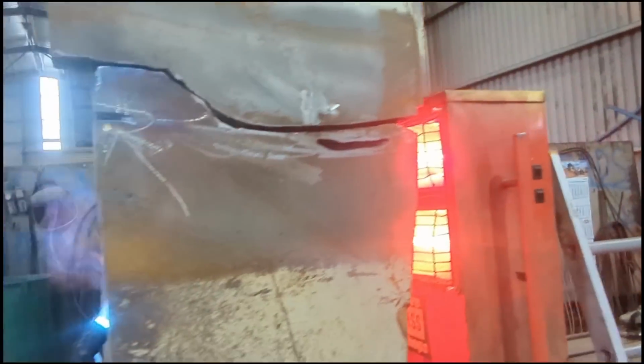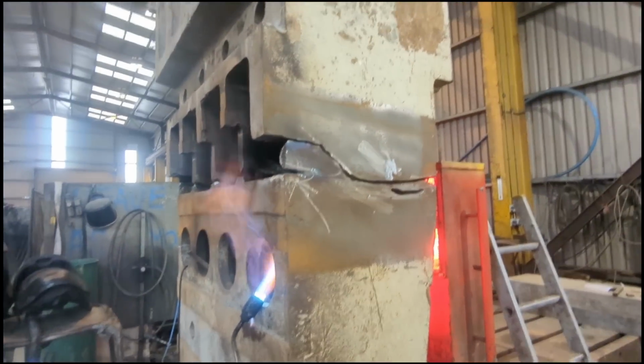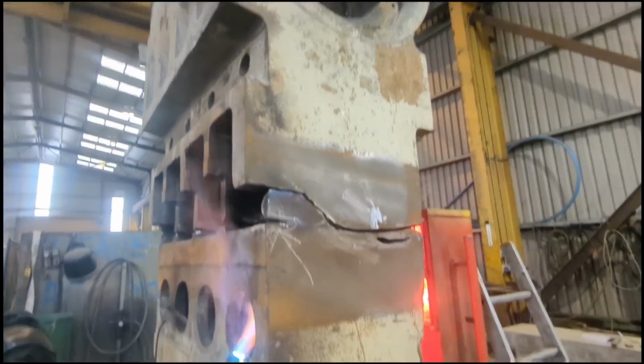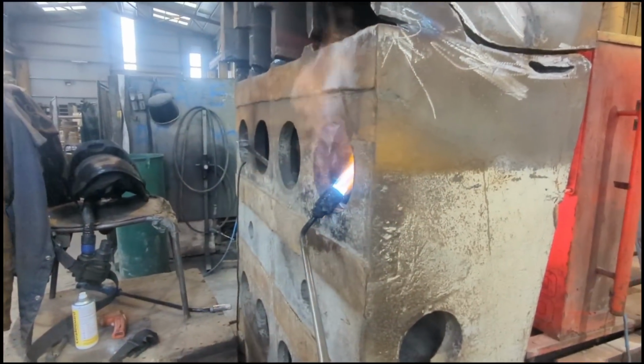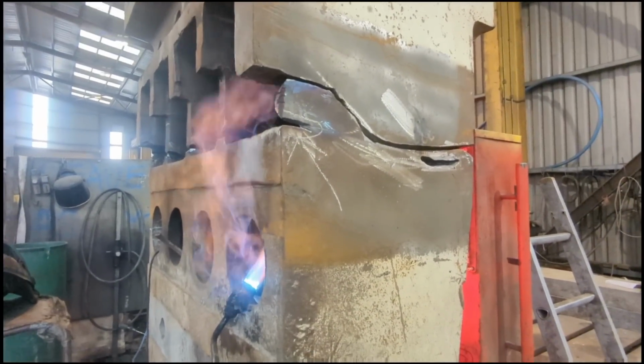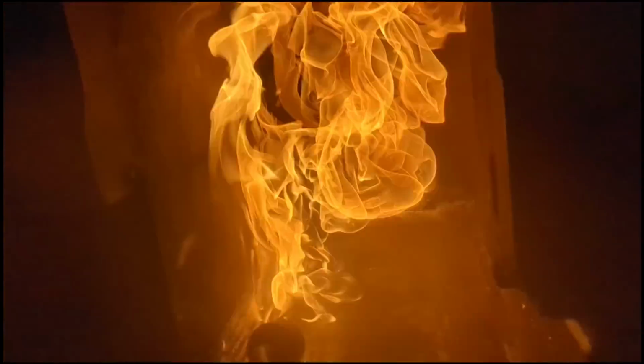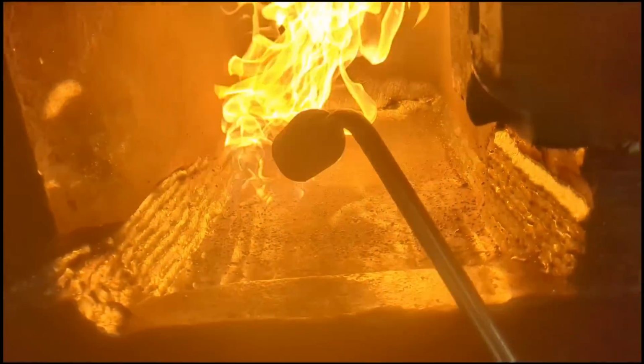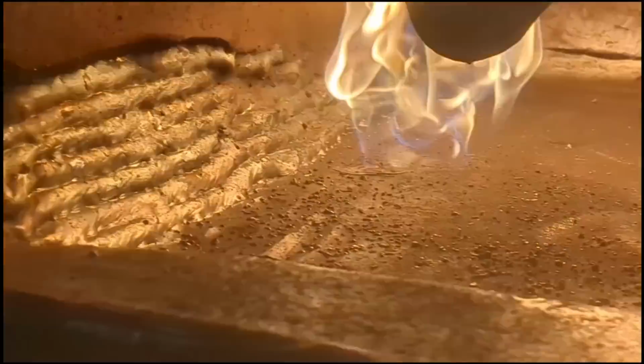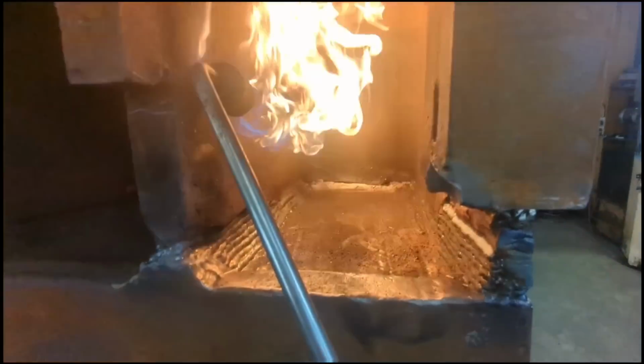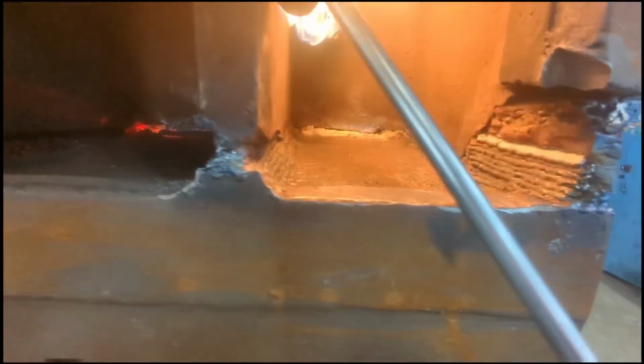Now I've got the propane gas heating torch and a 2 kilowatt heater to maintain temperature whenever I'm not welding or on lunch break. This will take absolutely hours. So preheating is critical. It's critical that there is not too much localized intense heat in one area. There has to be a gradual gradient across all of the areas to be welded as much as possible. I'm doing this with the propane torch and the electric heaters. I try to get the whole entire thing up to as close to 150, 180, 200 degrees as possible.